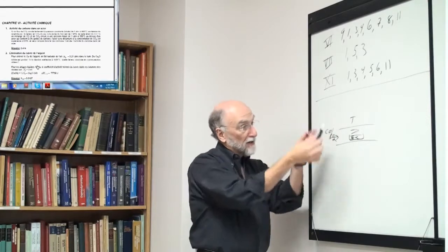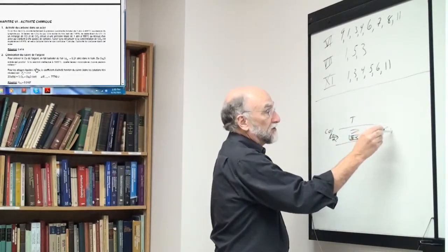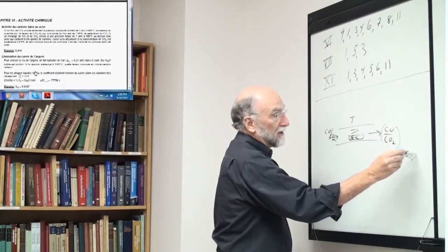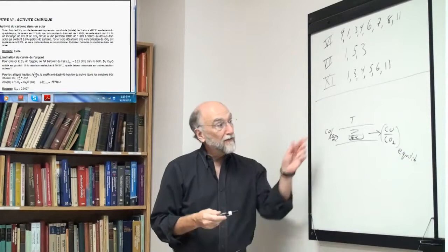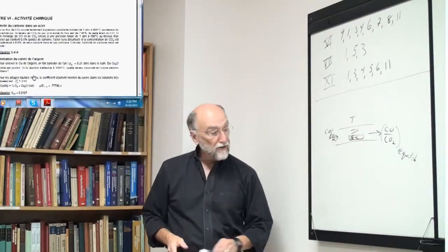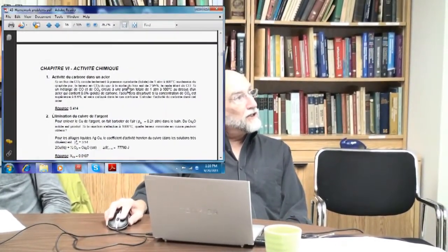The gas and the carbon equilibrate, and the CO2 at the exit is assumed to be the value in equilibrium. So you assume that at the exit you're measuring the CO2 that was at equilibrium with the carbon in the steel, so you've got to pass it slowly, of course, and let it reach equilibrium. Then you measure the CO2 ratio outside. So we actually did 2 experiments.